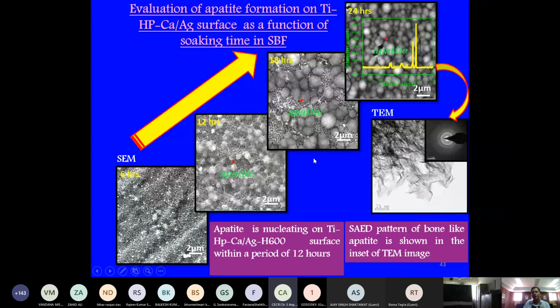While evaluating the bioactivity of the sample, when we soak the sample in this simulated body fluid, or SBF, you can see how the apatite or bone formation started happening within 12 hours of immersing in this body fluid. This indicates that with the modification I am doing to titanium or titanium alloys after 3D printing, we are able to induce bioactivity when soaking in the body fluid solution. And after 24 hours, the entire surface is covered with new calcium phosphate or bone formation.